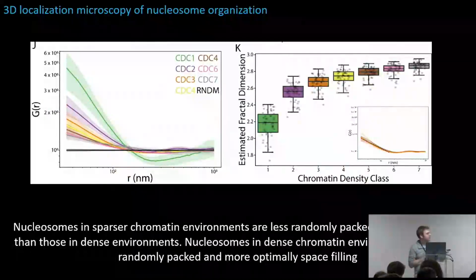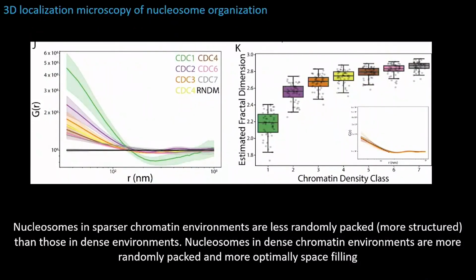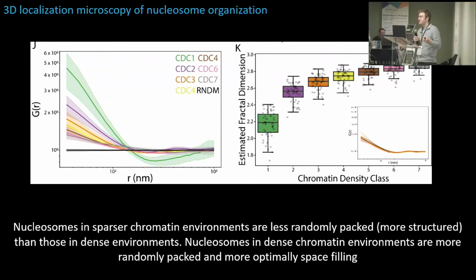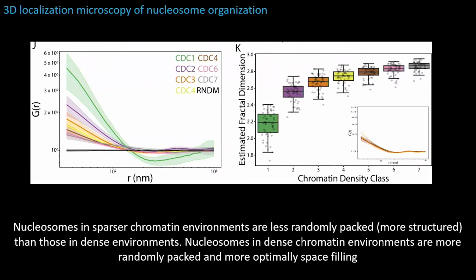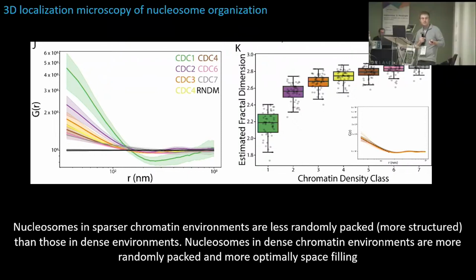What's interesting, though, is if we plot this as a function of chromatin density class, we see a very clear trend that nucleosomes display different physical packing in these different chromatin density environments, regardless of their underlying density. So they do seem to utilize different packing strategies and different organizational principles in sparse euchromatic versus dense heterochromatic regions in the nucleus. And what we find is that nucleosomes in sparser environments are less randomly packed. They're more structured than those in dense environments, and those in dense heterochromatin environments are more randomly packed and optimally space filling.